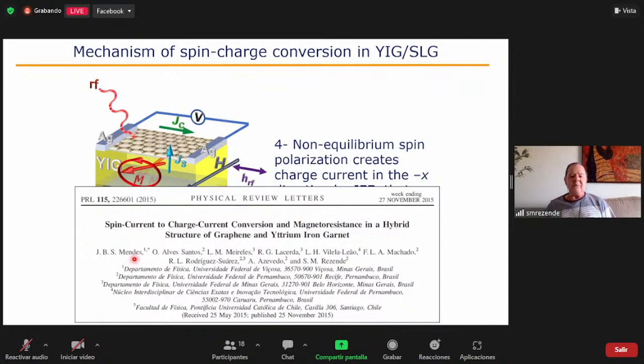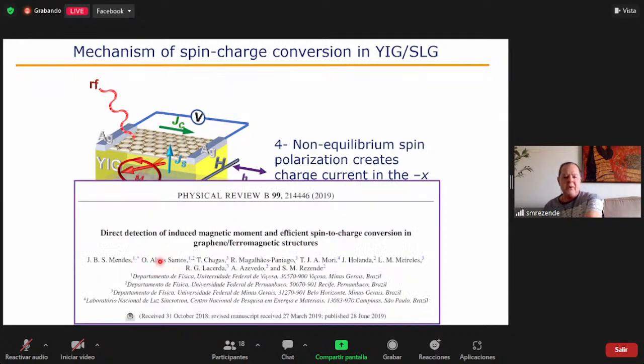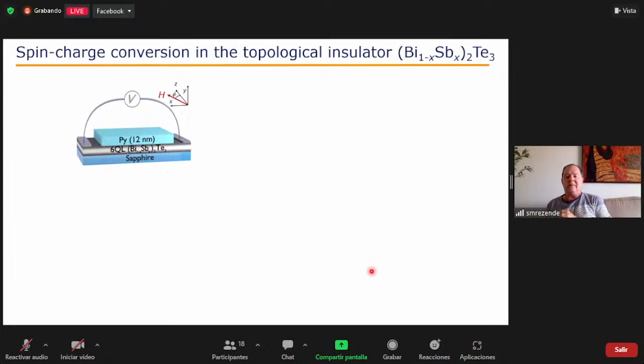He interacts with many people, and he continued to do this work, and we published a more detailed paper a few years ago involving experiments done at the synchrotron source in Campinas. Well, we also did, thanks to Joaquim initially, experiments with several other materials, like a topological insulator, this one here, bismuth, antimony, and tellurium, which was grown on a sapphire substrate.